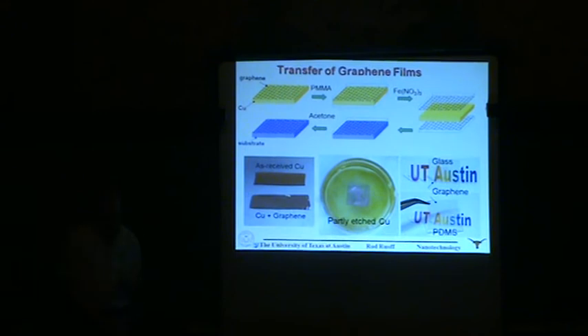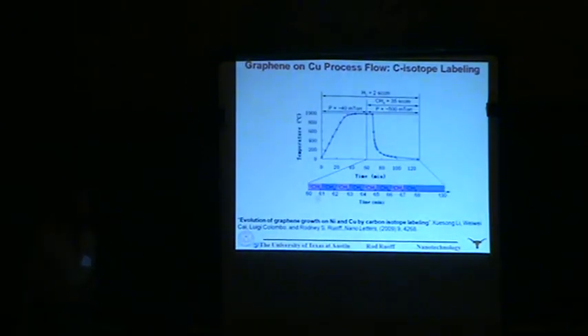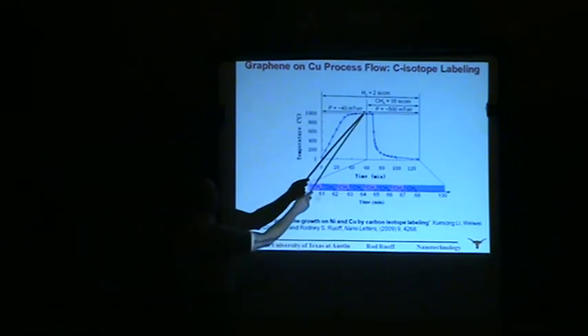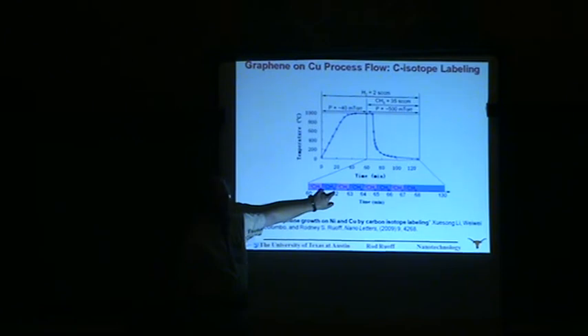So clearly, that suggests that it wasn't by precipitation, because the 125 micron thick foil would appear thicker, like bilayer, trilayer, etc. So we invented this approach where we dose with isotopically labeled methane. And Harry had mentioned the benefit of using C13. There's a great benefit here in understanding growth kinetics and also the mechanism of growth. So in this regime where we first introduced the methane before cool down, we're introducing C13 methane for 1 minute, and then I'm calling this C12, but it's just normal methane. So there's only 1.1% C13, and so on. Every minute, our flow controllers are switching between the two types of methane.